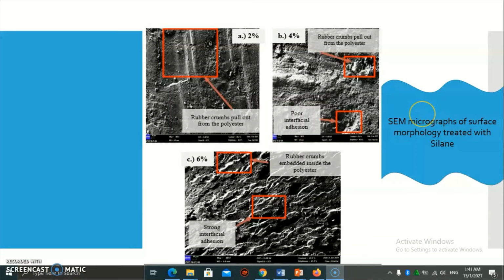Okay, this figure shows the same micrograph of surface morphology treated with silane. The first figure is 2% silane treatment, then 4% silane treatment, and 6% silane treatment. For the 2% silane treatment, as you can see here, the rubber crumb pulls out from the polyester, and for the 4%, the rubber crumb pulls out from the polyester with poor interfacial adhesion. For the 6%, the rubber crumb is embedded inside the polyester with strong interfacial adhesion.